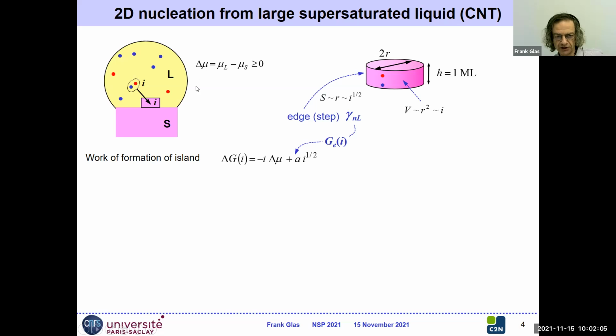So the supersaturation delta mu, positive, is favorable to this transfer, but of course there's a price to pay for it. Each time we create an island, we have to generate the edge of the island, which has a specific energy, which I will call gamma NL or gamma E. But here we have a first example of the differences of dimensionalities. The volume of the island scales with the number of pairs I that I have transferred, but the edge scales only typically with the square root of this number because it's an edge feature. So if we calculate the work of formation, we have a negative term, which is favorable to the formation of this island, which is simply the product of the number of pairs that I have transferred times the difference of chemical potential. But we have a positive term, which opposes the formation of the island, which scales as the square root of the number of pairs.